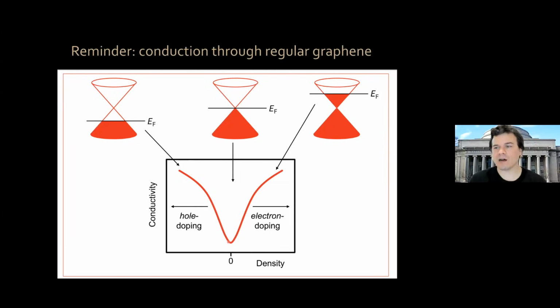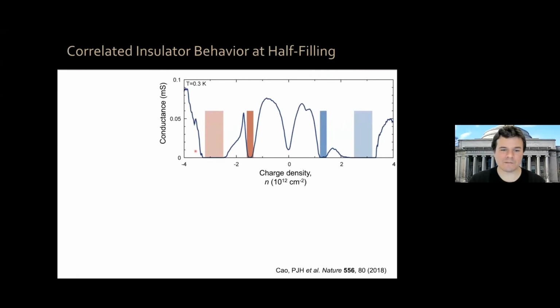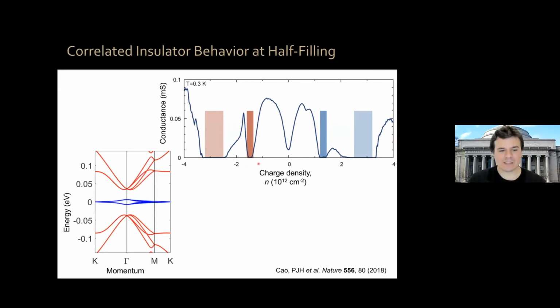Let me show you now what it looks like for magic angle graphene. So here we have conductance for an actual magic angle graphene device versus charge density. This is charge neutrality. You can see that near charge neutrality, the system still remembers it's graphene, so it has this V-shaped conductivity, but check what's happening at all of these other regions. The conductivity goes to 0 in many places, okay? So what is that? This is the electronic structure of magic angle graphene.